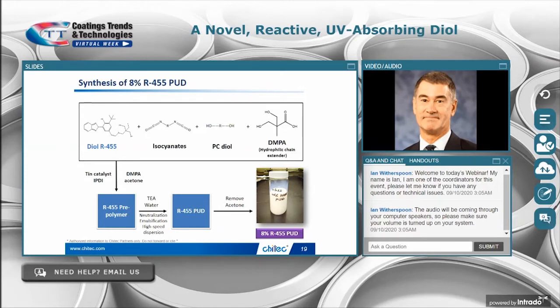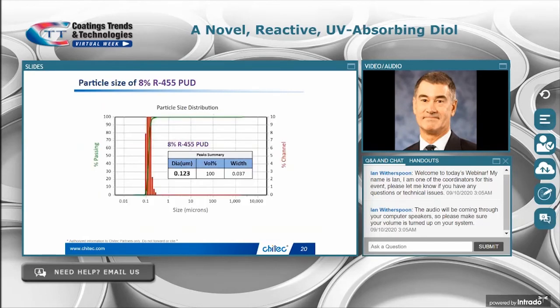Here on this slide, we're showing a polyurethane dispersion where we just insert the R455 into the urethane as a diol monomer. The PC in this example is a polycarbonate diol, and the DMPA is dimethylolpropionic acid, which is a diol that also provides a carboxylic acid for a later neutralization and salt formation to give you good dispersibility in water. This is a normal strategy for waterborne. Stripping removes the acetone solvent, which was necessary to dissolve the DMPA during the polymer synthesis. So this is a fairly normal polyurethane dispersion synthesis strategy that we just looked at.